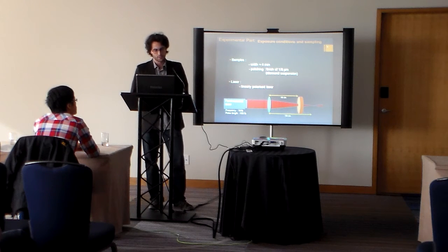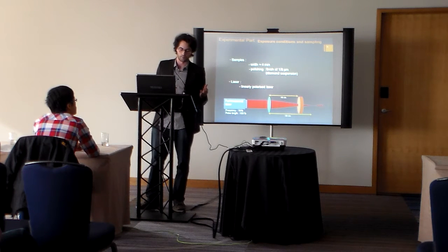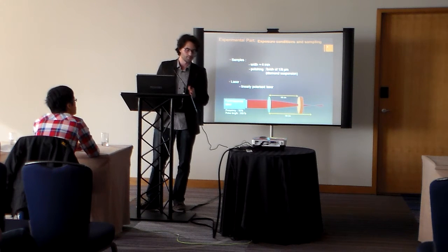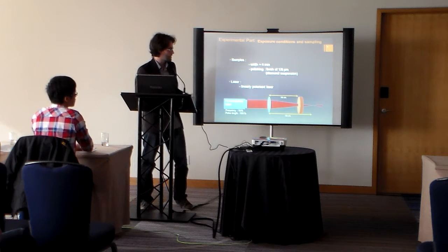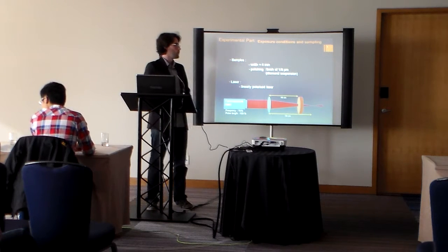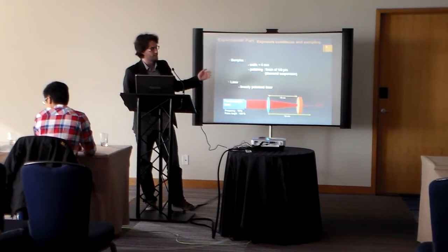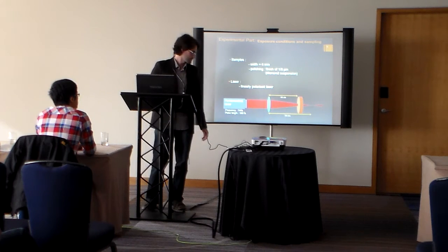So for my project, I used samples that I cut from a preform, basically a big cylinder of glass, made by Mohamed El Amraoui. I cut it with a width of about 4 millimeters, and I polished them to a finish of 1/8 of a micron with diamond suspension.